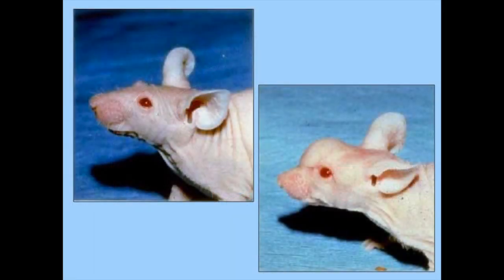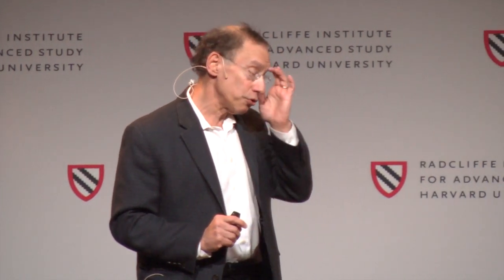Chuck Vacanti, who was actually in the newspaper today, worked with us. He was one of the two people behind the recent discovery of how acid can convert certain cells to stem cells. Going back to the 1980s when he started working with Jay and myself, one of the things he did was make new cartilage. Here, using nude mice, we redid this animal's skull, and here, this one's cheek. If you open the animals up, it's pure white glistening cartilage, and histologically it also looks like cartilage. However, the mechanical strength is not as good as you'd want for, say, a runner, but there are various things you can do from a cosmetic standpoint.